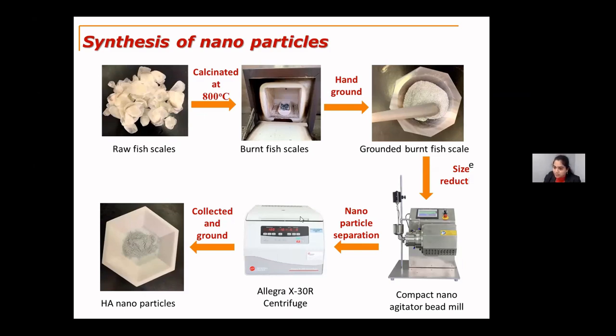This is a solvent based, or solution based, nano bead mill. So I use distilled water to cool down the temperature, and using the distilled water, the macro particles of these fish scales were sent into this nano agitator bead mill, and that was milled for 1 hour. After milling for 1 hour, we collect the nanoparticles of the hydroxyapatite along with the distilled water, and then we centrifuge it to separate the nanohydroxyapatite and water. The collected nanohydroxyapatite is dried and then again ground using the mortar and pestle, and then we get the nanoparticles of the hydroxyapatite. So this is how we synthesize the nanoparticles of the hydroxyapatite.